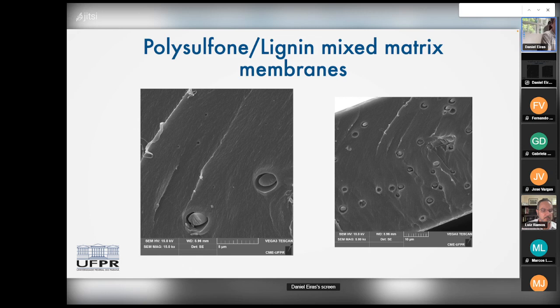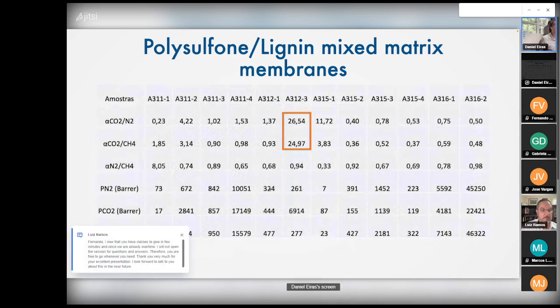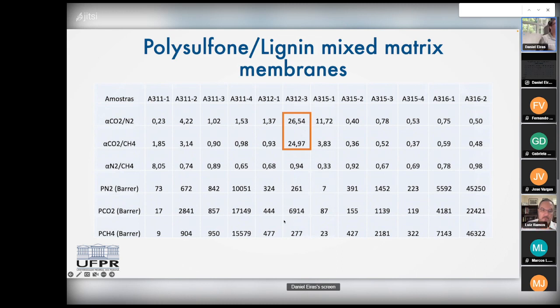Those defects are very difficult to control. It's very difficult to avoid those defects. And what happens is that some membranes have defects, other membranes don't have defects. Those that don't have defects end up having a good selectivity, although a smaller permeability. Those membranes that have defects end up having a very small or no selectivity at all.